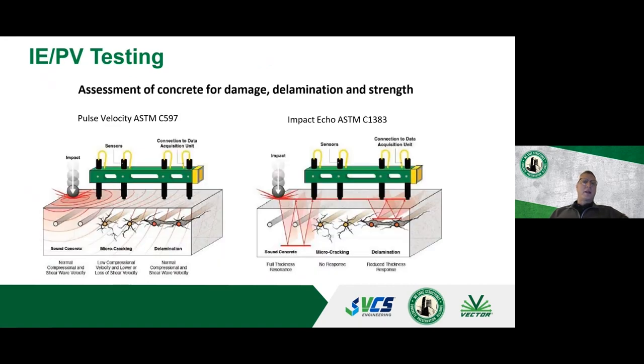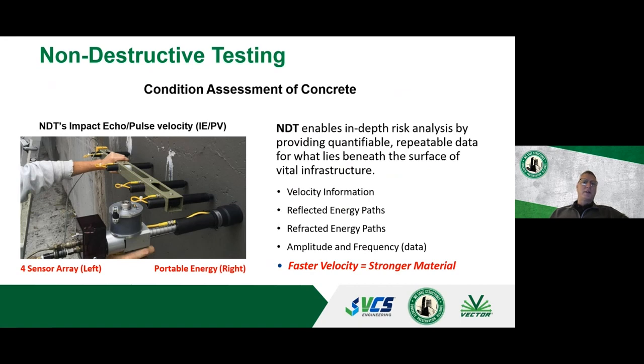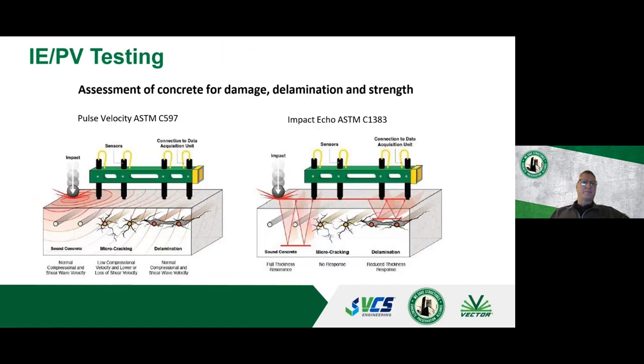And then you have a sensor array. So if you go back to this slide right here, you see in his right hand the projectile. So that's going to be firing a known weight steel ball at a known velocity at the concrete. And then you have 4 array sensors in his left hand that is picking up that energy wave that's moving through. So pulse velocity is measuring it as it's moving across the concrete, and I won't get really deep into this. And the impact echo, which can be done at the same time with those devices, actually will measure as that sound wave goes up, down, bounces within there.